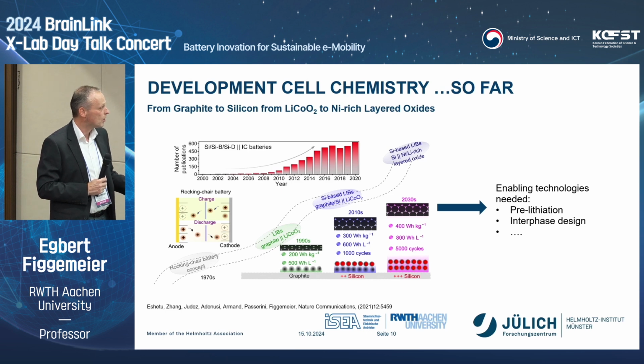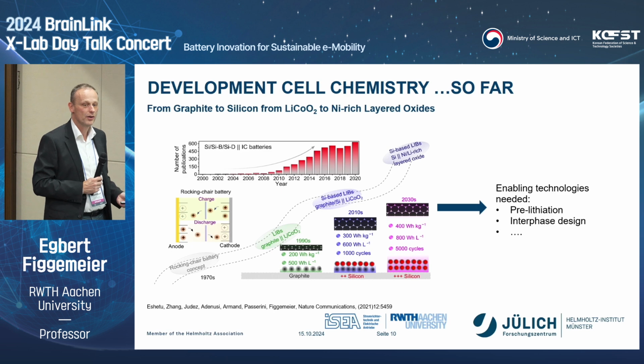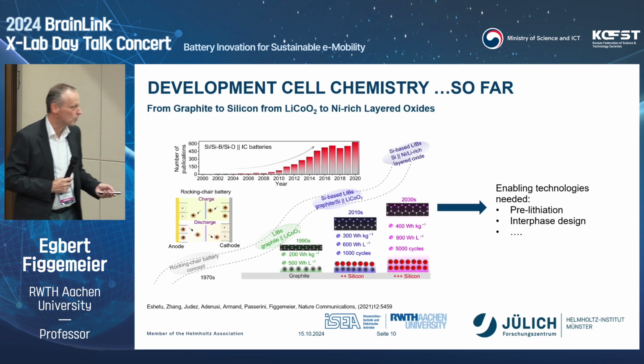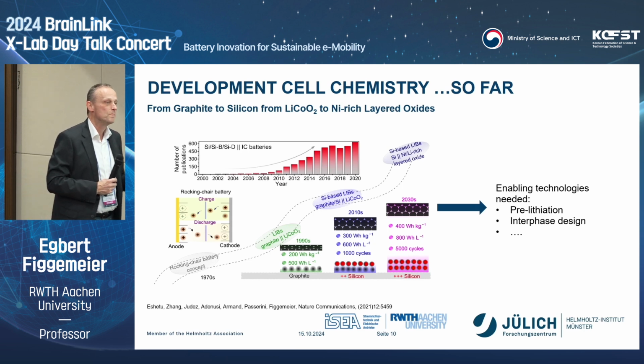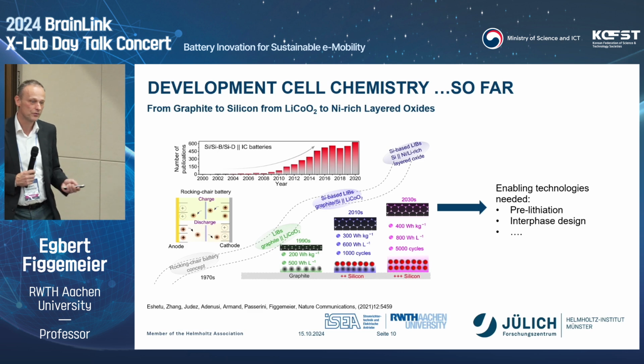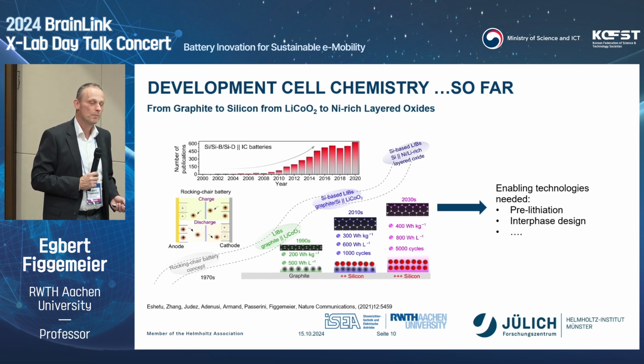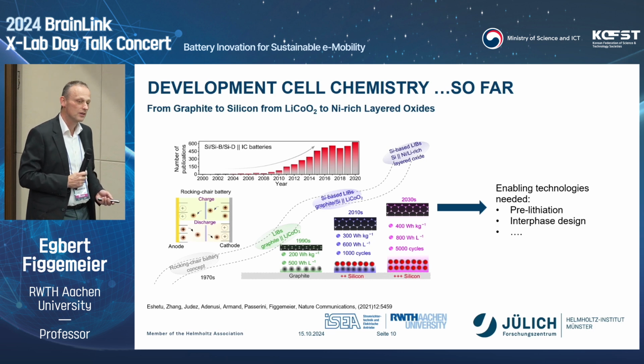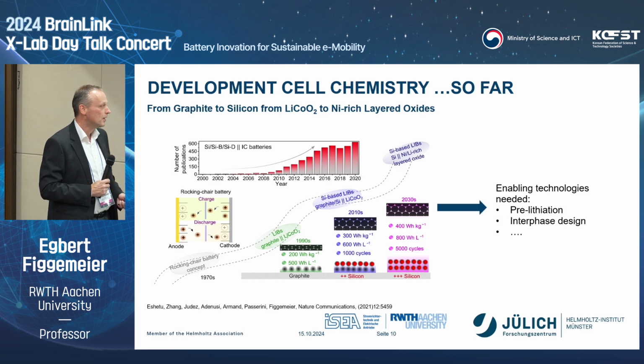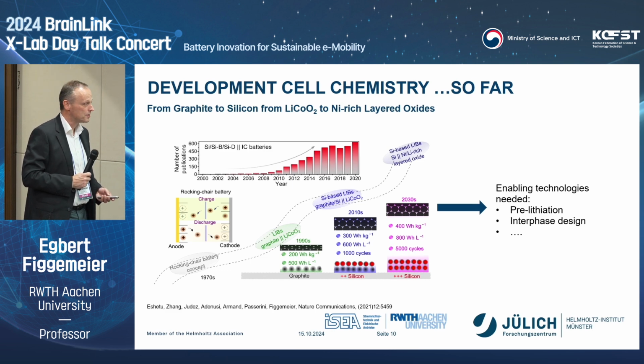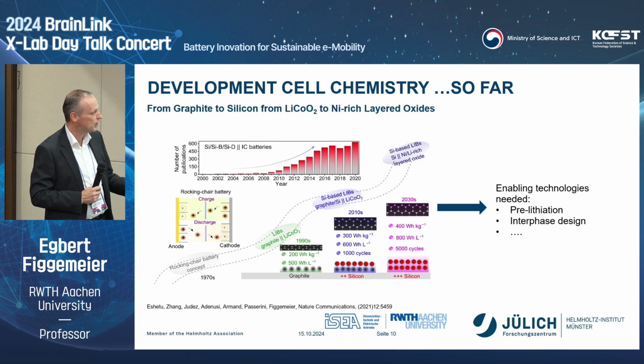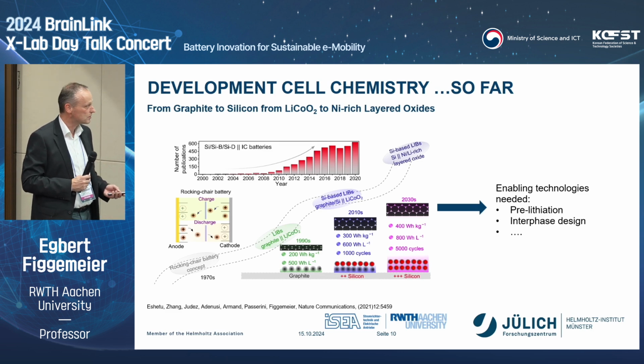And you need, let's say, this was, or it is the obvious roadmap towards very high energy density and specific energies. So I think every large OEM has this on the track or on their roadmap. Let's say the 400 watt-hours per kg with a high silicon content. But you need a lot of also enabling technologies for this. We have seen the interface stabilization of silicon is a tough one. And 20, 30 years of research have not really solved this problem. There are some cells on the market with low silicon, but they still have issues because of the expansion issue. The alloying is there, the volume expansion in particular, breaking the SEI, is compromising safety and lifetime. So we're working on this. We work a lot on pre-lithiation to compensate the irreversible losses.